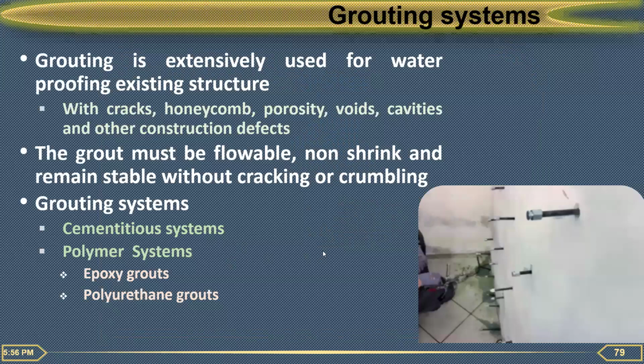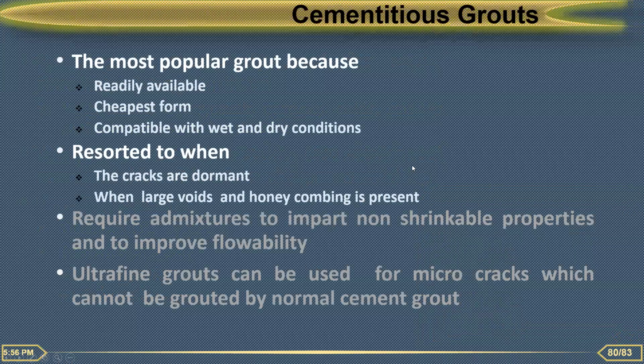And popular grouting systems are cementitious grouting, as we all know. Then polymer grouting systems. Popular ones are epoxy and polyurethane grouts. The cementitious grout is still the most popular one because it is readily available, cheapest, and compatible with many surface and substrate conditions. But it can be resorted to only when the cracks are dormant. If the cracks are expanding or widening, it's of no use, and it is especially useful for large voids and honeycombing. And this grout uses admixtures to impart non-shrink properties and improve the flowability.